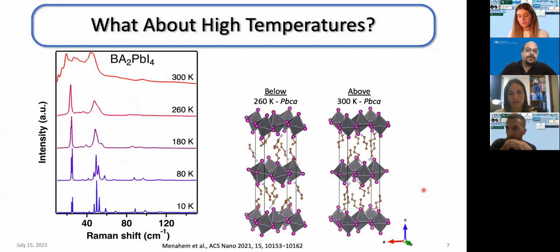So up until now, we talked about the low temperature phase. What about the high temperature phase? What happens when we undergo a phase transition? So going back to the Raman scattering of butylammonium lead iodide, we see that the spectra before the phase transition and above the phase transition are very dissimilar. They are very different. But if we look very closely at the low frequency range, we see some similarities.